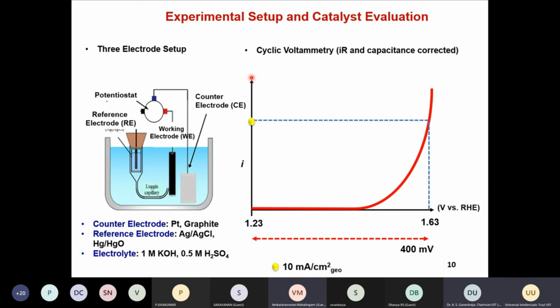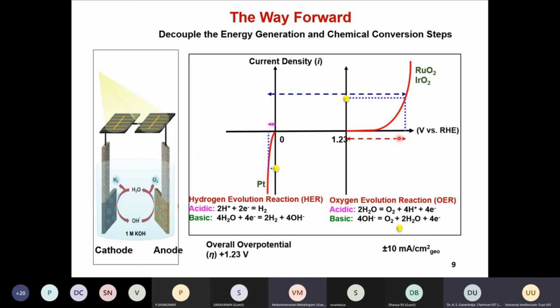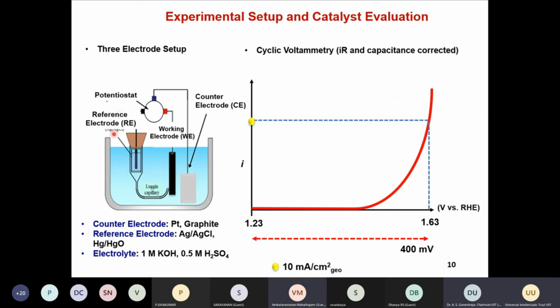So this is a typical setup used to measure this activity. The potential which we measure, we call it the overpotential. That means the extra potential required to achieve this water splitting. This is a typical 3-electrode setup. I think most of you are familiar with it. We have a working electrode, a reference electrode, and a counter electrode. Platinum is used as the counter electrode, the working electrode is your catalyst, and the reference electrode is mostly Ag/AgCl. You connect to the potentiostat, apply potential, change the electrode potential and see how the system reacts. What you measure is the overpotential required to achieve this water splitting. This is a typical cyclic voltammogram. It's not a complete CV, it's half of it.